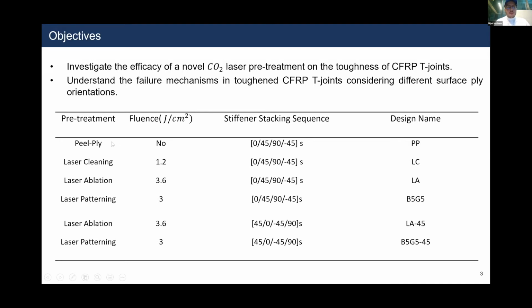So I had 4 different pretreatment techniques. The first one was a baseline peel ply pretreatment, and the other 3 were laser-based pretreatments: a low fluence laser cleaning, a high fluence laser ablation, and an alternating pattern between laser cleaning and laser ablation. For the stacking sequences, we used a quasi-isotropic stacking sequence, which had a 0-degree ply on the surface. I also did 2 other tests on T-joints, which involved having a 45-degree ply orientation on the surface to understand if anything would change by having a 45-degree ply on the surface.